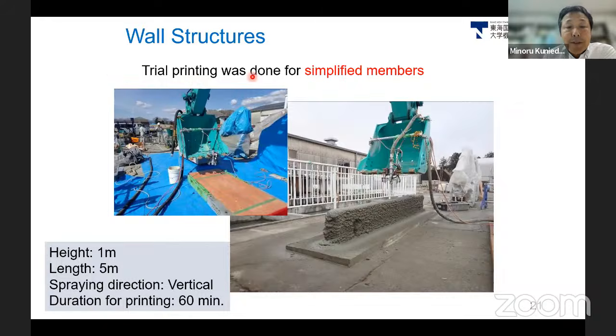That trial printing was done for simplified members because this backhoe is, of course, programmed, but not appropriate for complex members and shapes. So the first one is just a wall with a straight shape, and the height is 1 meter and the length was 5 meters, and the spraying direction is vertical, as you can see. And the duration for the printing is only 60 minutes.